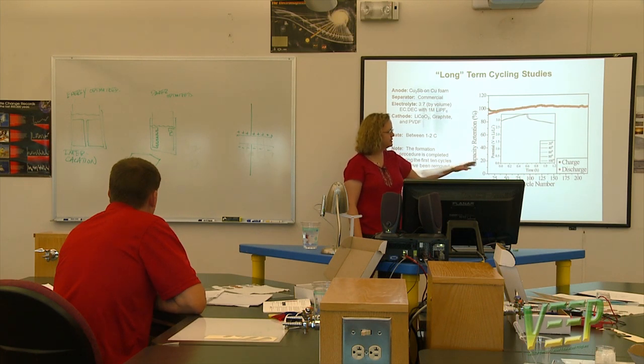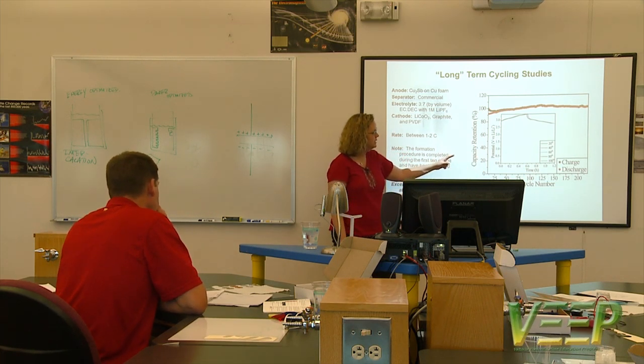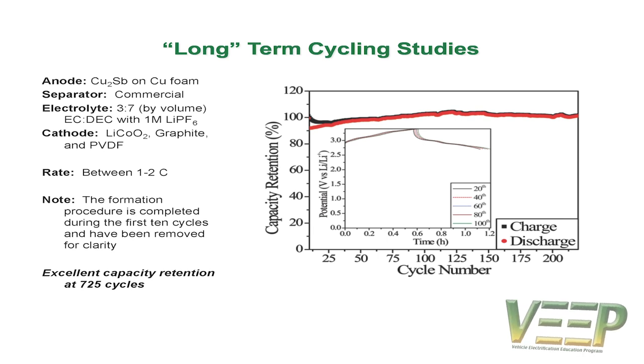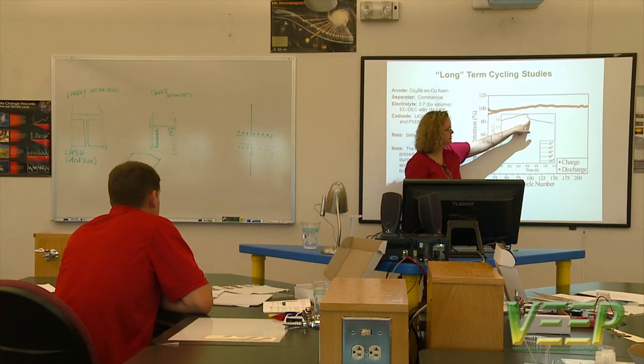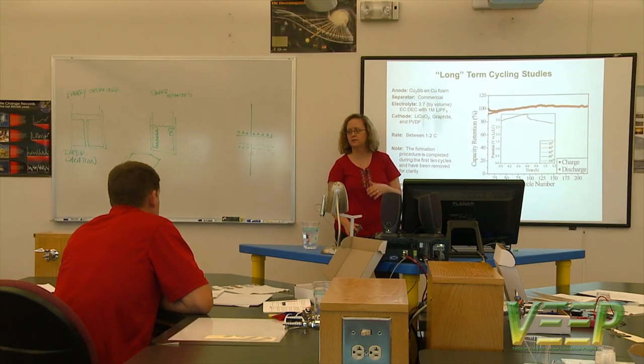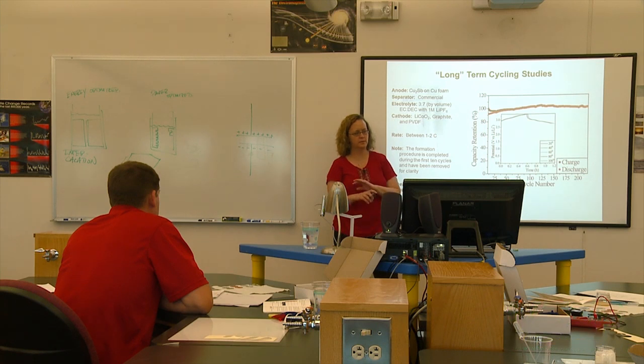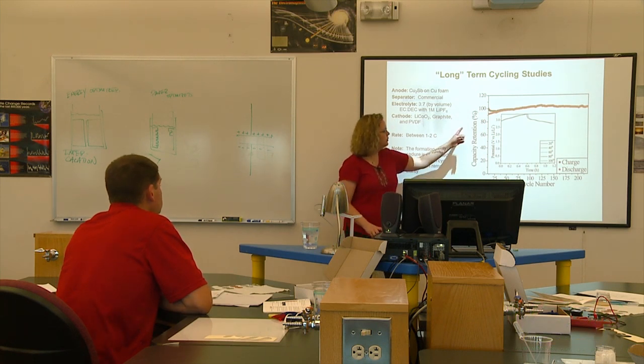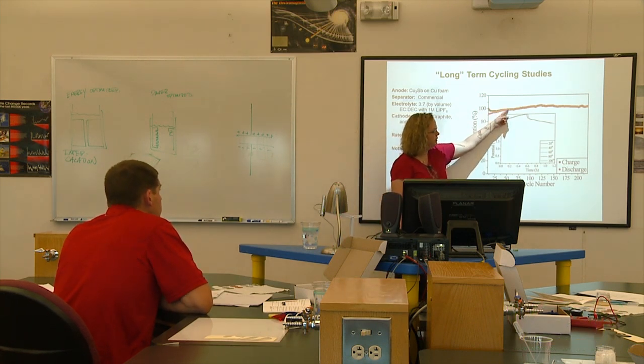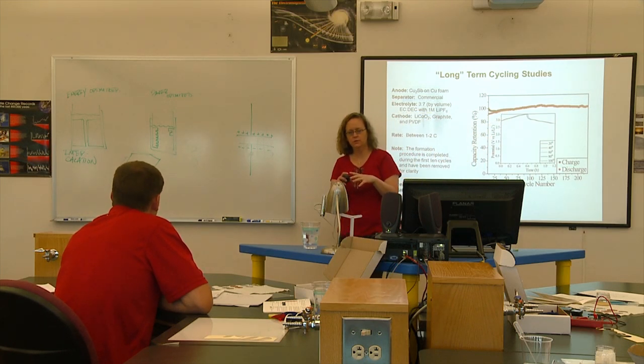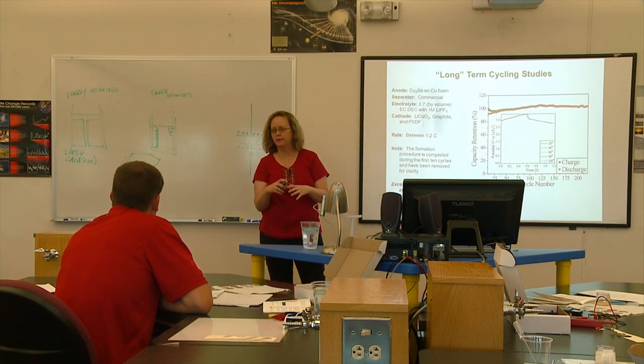There's a whole forming process I'm not going to talk about, but what's important is that if we look at voltage versus lithium metal as a function of time, every 20 cycles it doesn't change. All you need to get is that all these lines are the same. That to us is telling us our material's not degrading. It's acting exactly as it should. If we plot capacity retention, you see it's getting better over time. That's because we are roughening it every time it expands and contracts. And the rougher it gets, the more surface area it makes. And so it can go even faster.